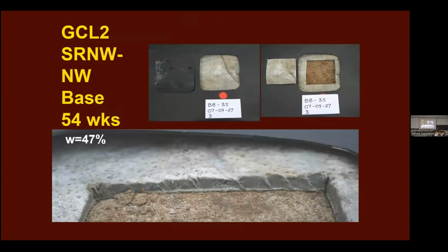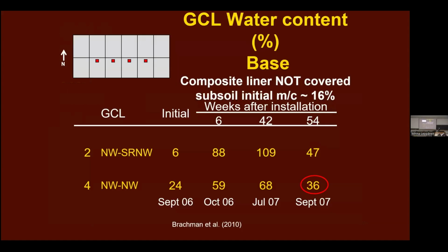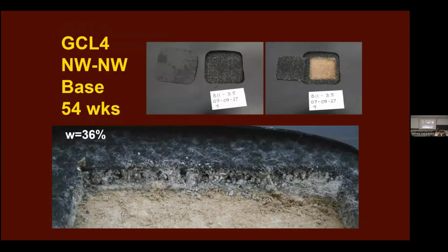So this is what it looks like at 47%. It still looks pretty good. It's just starting to crack. But it's got a very nice structure because it's been well hydrated in its history. Now let's look at a second product. And it started at 24, it went to 59, 68, and down to 36. It has a coarse-grained bentonite instead of a fine-grained bentonite. And the rate at which that hydrates depends on the nature of the bentonite. And this never got very hydrated. And you can see that it's still got the coarse particles. They've never formed a gel.